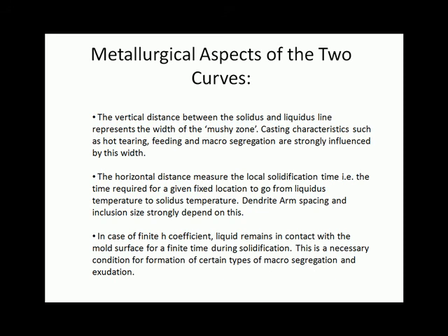Metallurgical aspects of the two curves. The vertical distance between the solidus and the liquidus lines in the previous two graphs represents the width of the mushy zone. By mushy zone, we mean the zone in which both solid and liquid exist together. Casting characteristics such as hot tearing, feeding, and macrosegregation are strongly influenced by this width.